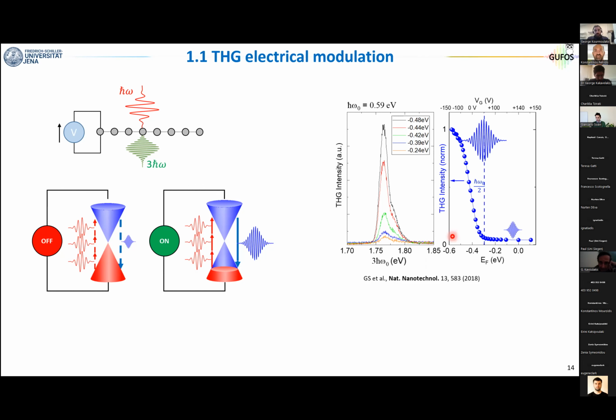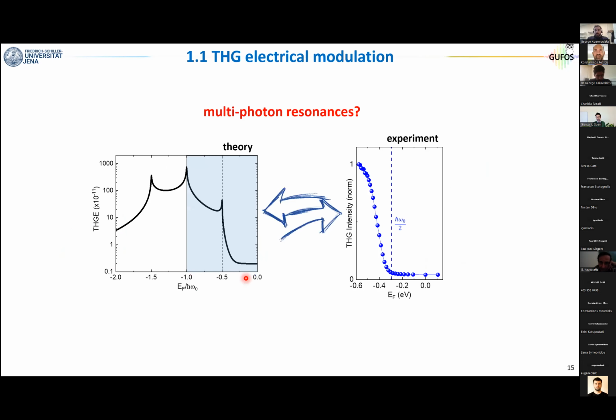So maybe I start from these questions to go on. But before I move on, I want to show one thing. I started from discussing this theory, where I say, okay, there are 3 very sharp resonances, and the first resonance is when the Fermi energy is equal to 2 times h bar omega, this one. And now we look at the experiments, and this line, that is exactly this condition here, is certainly not at the point where we have a resonance. So there is clearly a very big discrepancy between the theory and the experiments. So now you should argue either our experiments are wrong, or our interpretation is wrong, or something is missing.